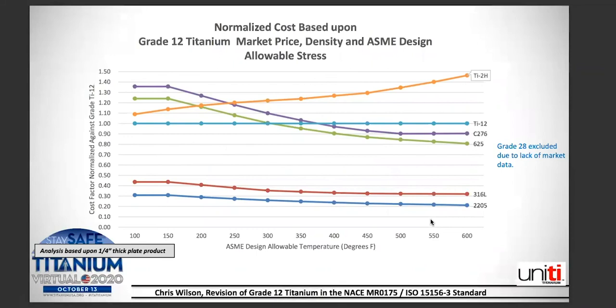Okay, so here's the chart. We looked at some various competitive alloys. I did not include the grade 28 just due to lack of market data and lack of availability. So that was not included in here. If you look at the orange line, that is our standard grade 2H. The blue line is the normalized grade 12 that becomes the standard in this example. So it's normalized at 1 across the board at every temperature. And then we chart the various grades at the elevated temperatures, giving the ASME design allowable properties.